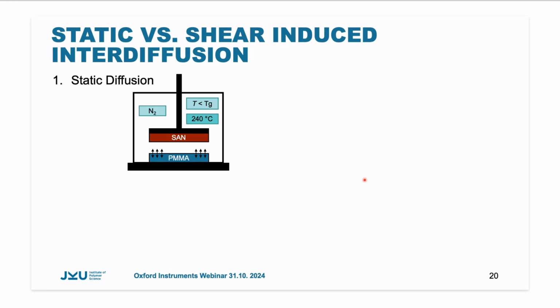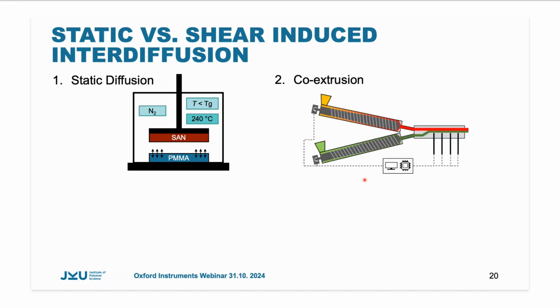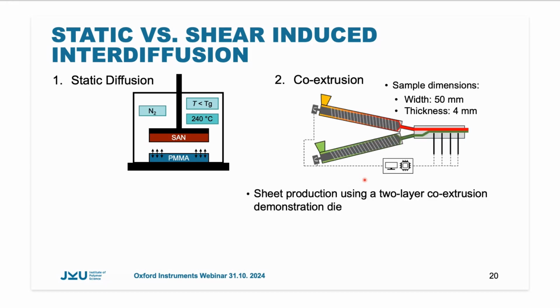Since we've proved that Raman spectroscopy and scanning force microscopy are suitable to investigate the interfacial layer, we would like to compare what is going on the static and under shear induced interdiffusion. Static diffusion I've shown you. This is our co-extrusion experiment. We used a special 2-layer co-extrusion demonstration die, which allows to produce sheets which have sample dimensions of width 50 mm and a thickness of 4 mm.